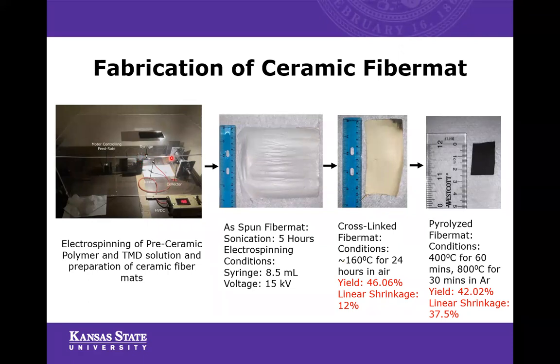Assuming that everyone here knows about the electrospinning process, I'll move on to the fibermat, which is obtained from electrospinning. Then this fibermat was cross-linked at 160 degrees Celsius for 24 hours in the presence of air. Then a small part of it was pyrolyzed at 800 degrees Celsius for 30 minutes in the presence of argon.